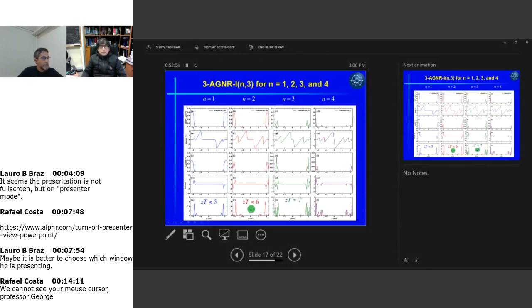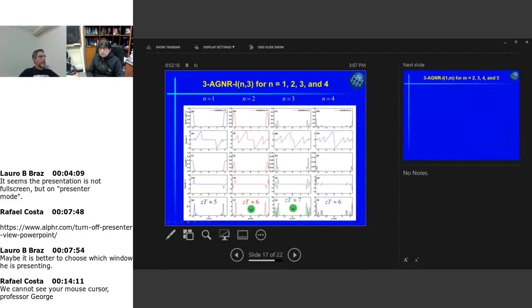We are happy with that. We go to a ZT value equals 7 here. We are even more happy. And the ZT value equals 6 here. So we showed already that by manipulating the parameters we could get a ZT equals 7 here, so you can improve your ZT by more than 10%. You may say, well, a little bit more than 10% is not much, but if you go back to that plot I showed you of the evolution of ZT in the last 70 or 80 years, there was a period of 30 years where ZT was stuck at 1 and there was no improvement at all.